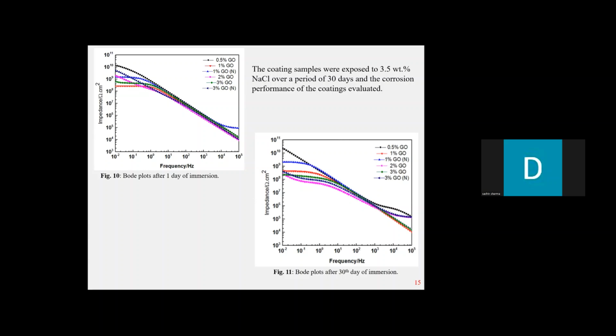So just to give you the knowledge of how we know how good the coatings are, we look at the y-axis. Anything between 10 to the power of 4 to 10 to the power of 5, the coatings are actually poor. 10 to the power of 6 to 10 to the power of 7, in that range, is considered moderate. However, anything above 10 to the power of 9 is considered excellent. That means it has provided an excellent barrier property for the coatings to withstand the penetration of the electrolyte ions.